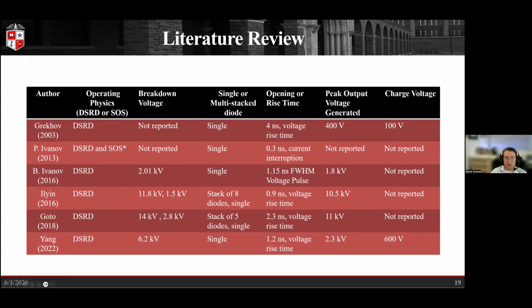Just a few years back, Ilion presented on a stack of 8 diodes at 1.5 kV each, giving us a total device breakdown of about 12 kV. So we can see a gradual trend towards these higher voltage devices, and that's one of the motivations behind this research. We can also see, since they are DSRDs, we are going to be looking at really fast rise times or full width half maxes, depending on what metrics the authors intended to publish. But we can see everything is on the order of single nanoseconds to even sub-nanoseconds for some of these demonstrations.